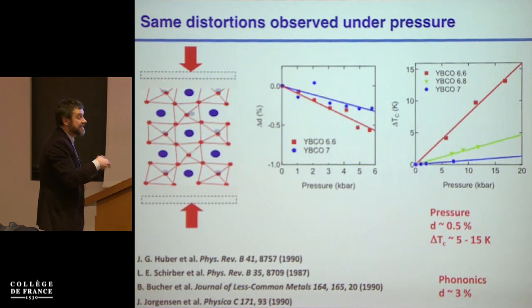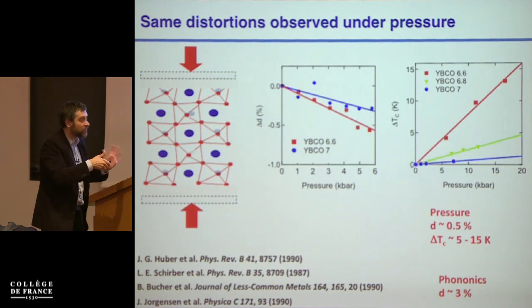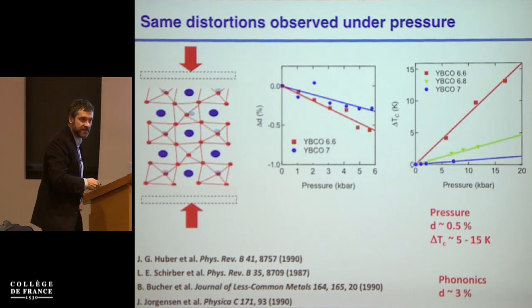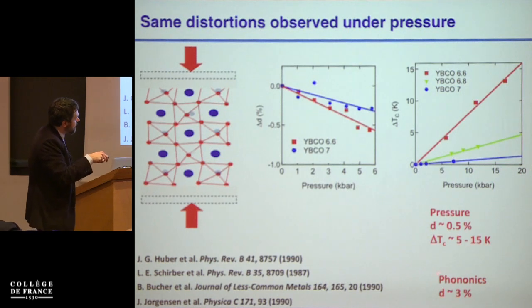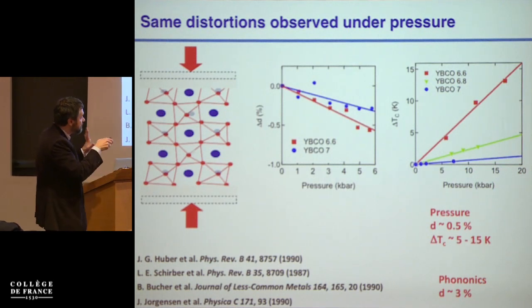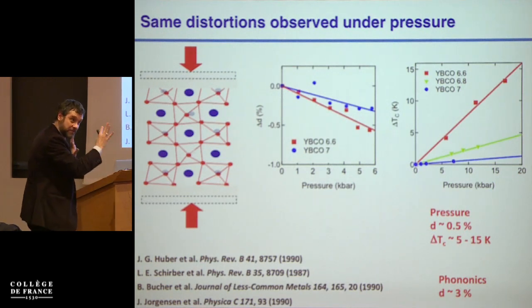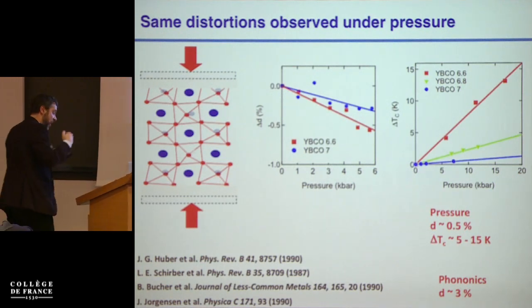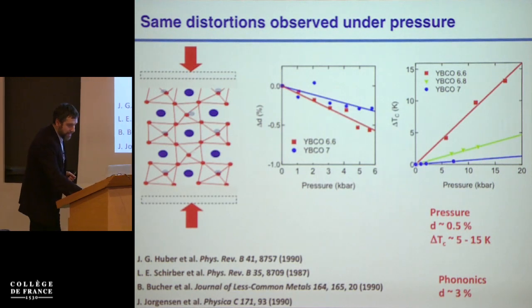on average in the same direction in which we observe it on average, except that we can drive it by, and this number was connected to a change in critical temperature by, say, anywhere between 5 and 15 Kelvin, depending on the details. Okay, by phononics, we could drive it in some cases between 1 and 3%, and this might be indicative that some of the same physics on average might be happening.